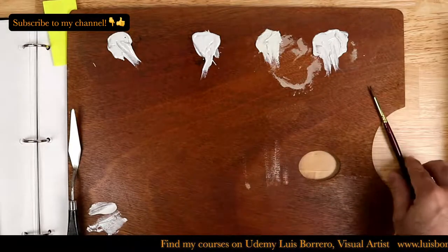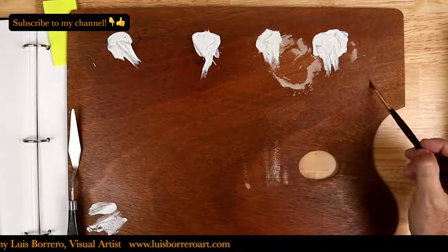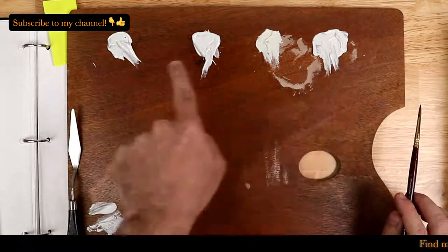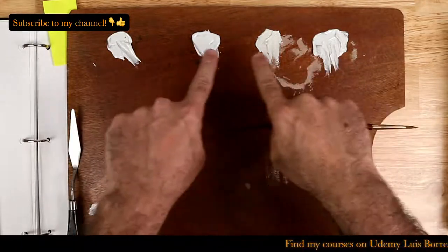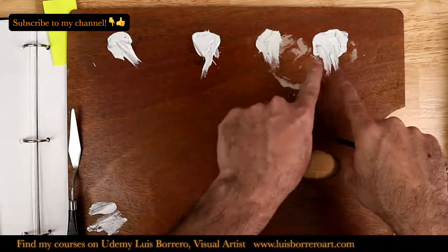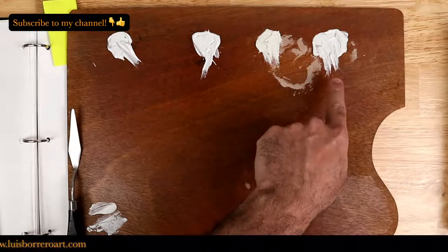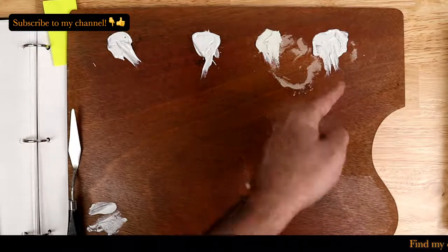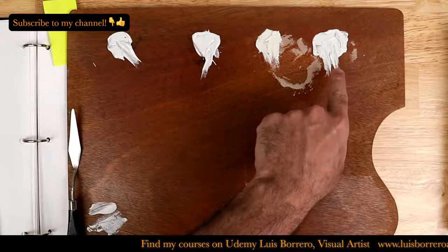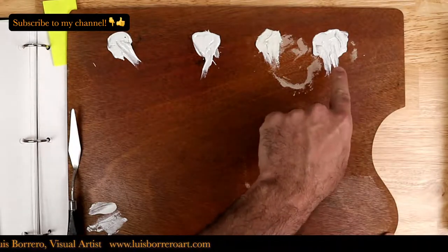So I like to use here a sable brush, and I want to show you. Let's begin with the samples I made. There are four samples here. Three of them have been ground for an hour, and one of them has been ground for half an hour. I have washed linseed oil as described by the old masters. You take the linseed oil and wash it with water, and it cleans all the impurities of the oil. That's what I did in the first sample.